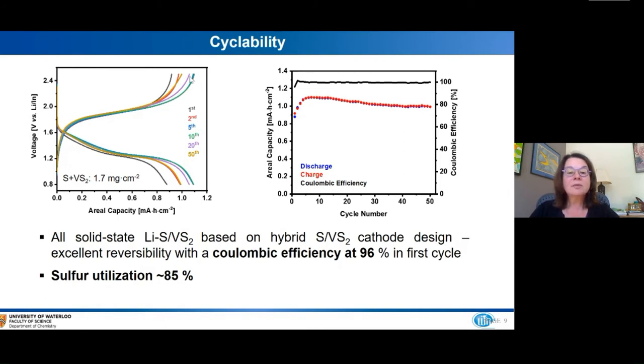The system is pretty stable on cycling. You can see that we initially have an increase in capacity, which we sometimes call creep, and then it is reasonably stable over 50 cycles. This is just showing the coulombic efficiency here on the right axis.